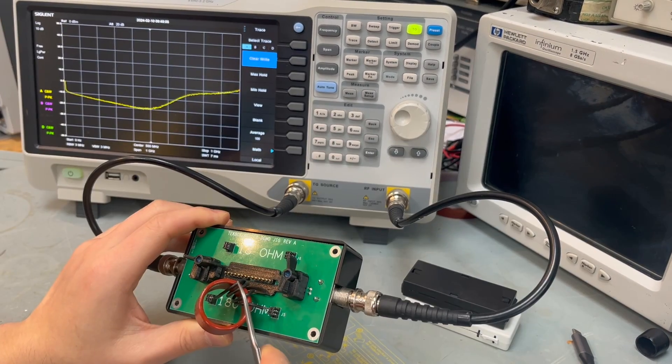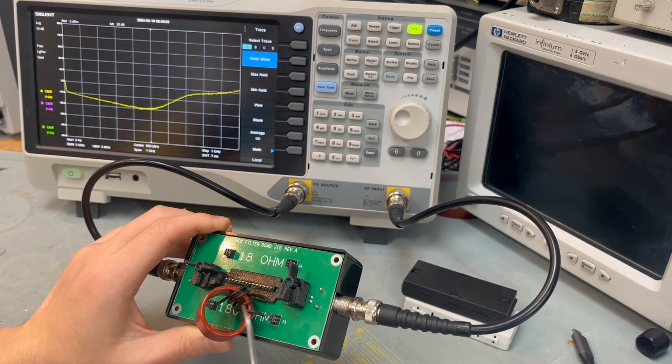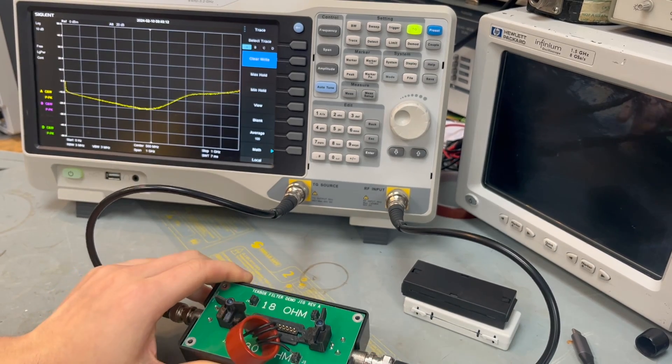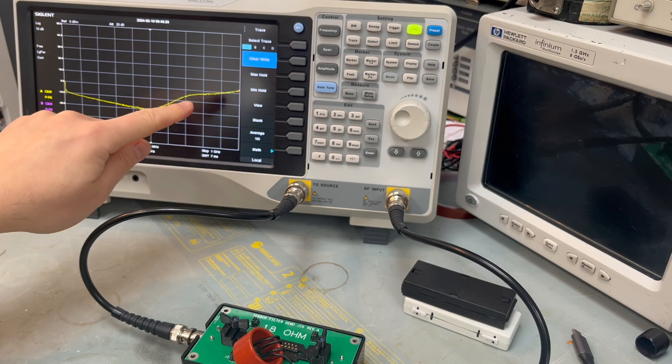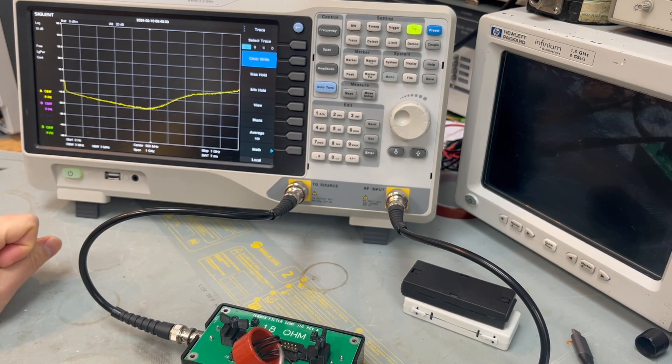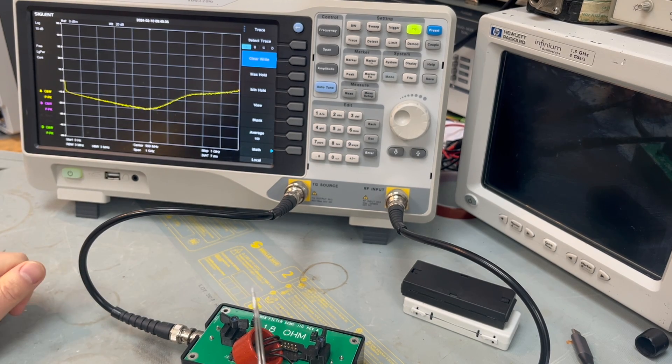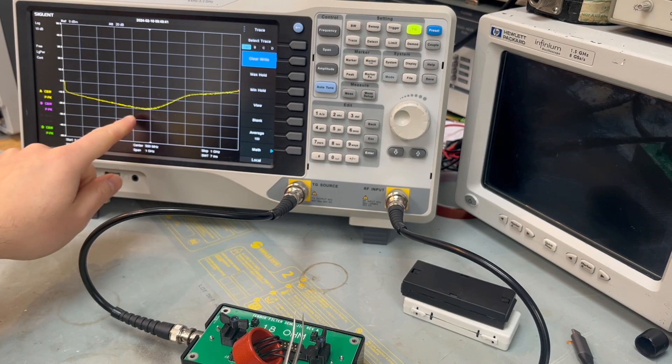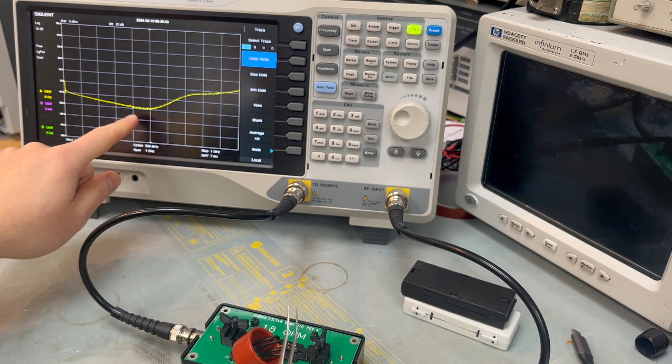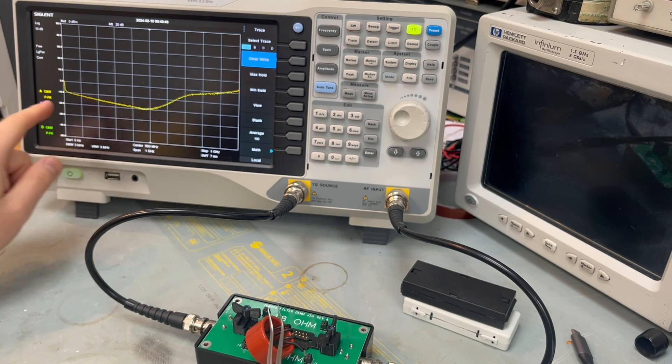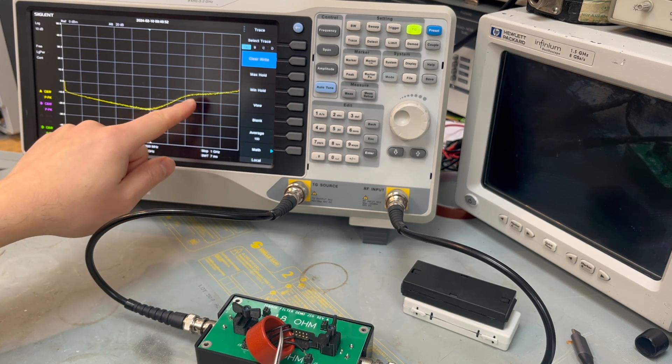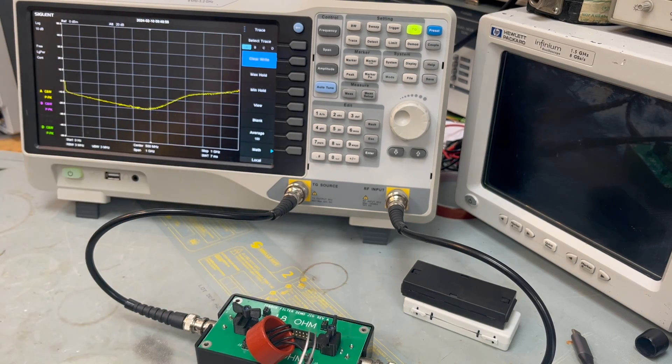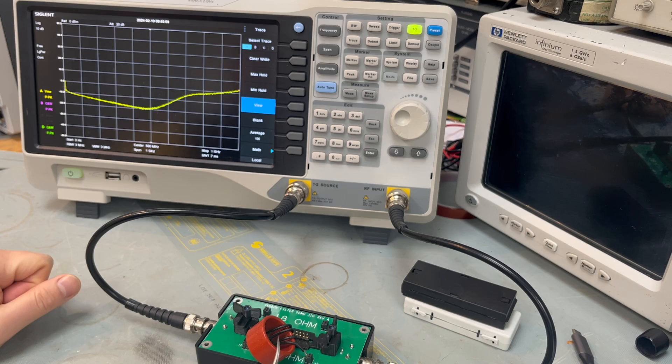Here it is a nanocrystalline material core. As you can see, one, two, three, four, four turns. It's a four-turn configuration of a nanocrystalline core. This is the impedance against frequency curve we've got from this four-turn configuration. First thing you notice, it's not bad. At 500 megahertz, we got 20 dB reduction of the signal. It is actually quite a wide frequency band. It starts from very low frequency and only stopped working at least for the four-turn configuration at 900 megahertz. It's pretty impressive. We can save this.